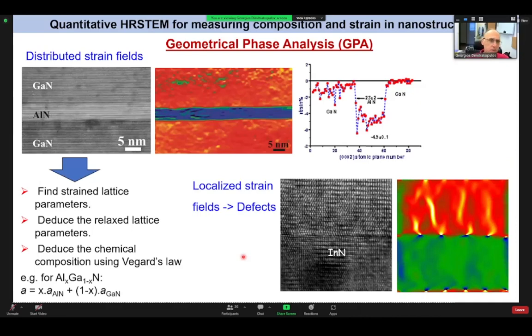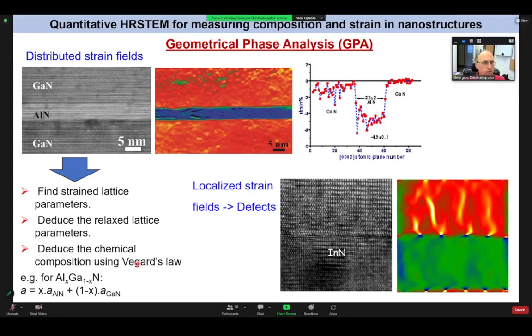So these are some results from GPA. With GPA, you can either characterize distributed strain fields, long-range strain fields, or localized strain fields. Localized strain fields are the defects, of course, the dislocations. So you can do both. If you are working with distributed strain fields, then you can find the strained lattice parameters in a place where the lattice changes. And then, if you know your elastic state, how the material deforms, you can deduce the relaxed lattice parameters. And for example, if you have a binary alloy, you can find the chemical composition by using Vegard's law. So this is an indirect way to find the chemical composition.